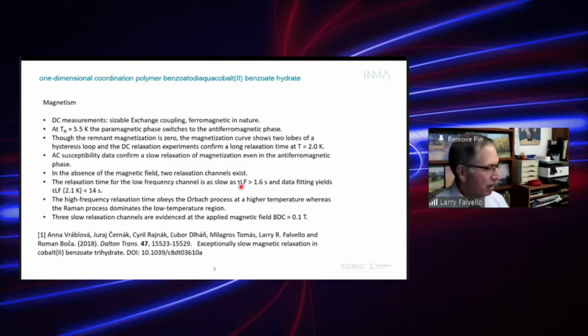Did you measure the heat capacity of this sample near the phase transition? No. No, okay. Because this could tell you about whether the dimensionality is dominantly 1D or it has some crossover between 1D, which might be the ferromagnetic component, and the three-dimensional order driven by the chain interaction. But yeah, it is interesting. It's intriguing. Yeah. And even more interesting that it's a compound that's been known for almost a century. Okay.